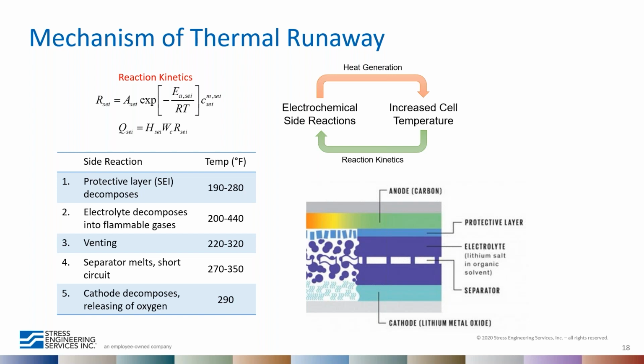The electrolyte is a hydrocarbon-based material. That flashing, if unabated, will continue to increase the pressure inside the cell and eventually rupture the cell itself. This is actually intended in some cases to reduce the risk of explosion. And then at an even higher temperature, the separator starts to melt and you get an internal short circuit. That dumps a lot of electrical energy into the cell in the form of joule heating, which can then cause the cathode to decompose, which in many cases releases its own oxygen, which can prevent suffocating style fire suppressants from working properly. So the abuse mechanism can either start at step one and move through the different side reactions, or in the case of an internal short, can actually skip to step 4, which provides the heat required to go back to step 1 and move through the sequence.